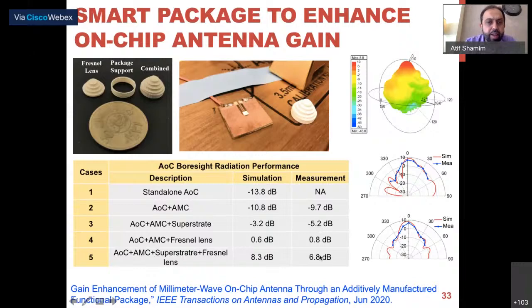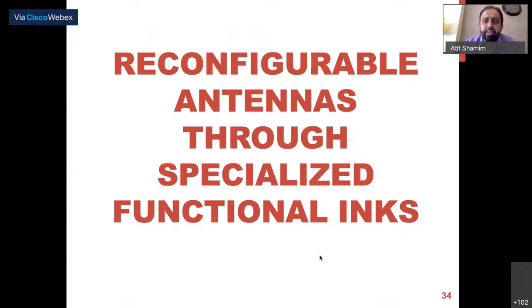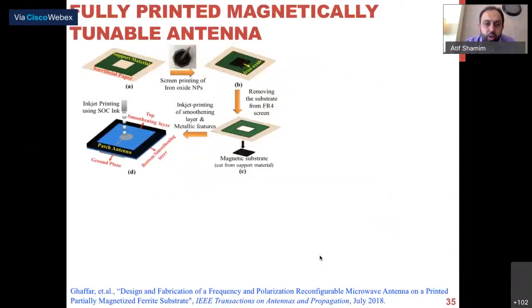Reconfigurable antennas: we did magnetic ink. We are able to make fully compatible magnetic substrates of our own, which are typically very expensive. We've characterized them, and they have decent magnetic properties. Here is an example where we showed a circular patch antenna on this magnetic substrate. The interesting thing is when you bias it, which means you apply a DC magnetic field, you get a change in the resonant frequency. You see two poles, because the RHCP and LHCP both split and go in different directions. So you could have two resonant frequencies going in different directions, and you could reconfigure them as per your liking on this magnetic substrate with decent radiation performance.